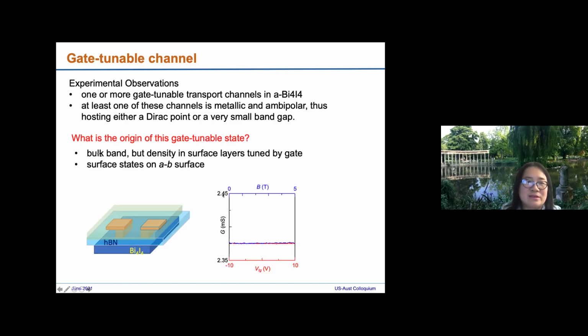We did a control experiment where we put holes in the encapsulating top boron nitride layer, so that we're only contacting the inside of the sample. Then we measured the conductance between these two contacts, and we find it has basically no gate dependence and no magnetic field dependence. This doesn't look anything like what we have seen in the normal samples that we fabricated. So this tells us it's not a surface state, or a bulk band that has some density in the surface layer that's tuned by the gate.